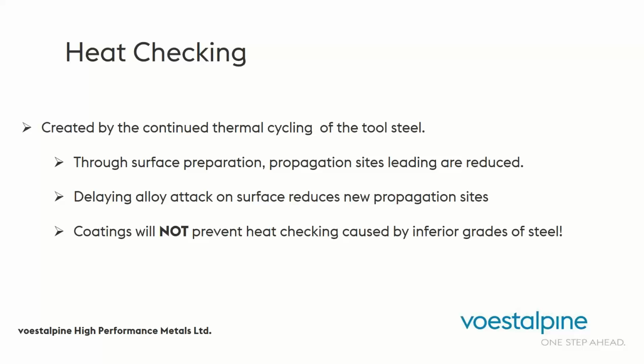When you expose the steel, you allow the attack of the abrasive and the corrosive action of the alloy on that steel, and then you get, as people say, coating failure. But it's not coating failure. It is a coating failure as a result of poor finish. So what do we do? We highly suggest one of two recommended surface applications. One is a high polish. And I'm literally talking about a mirror polish, as you would see in a mold.